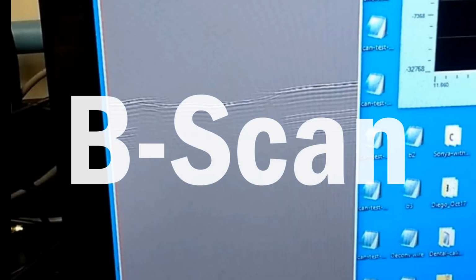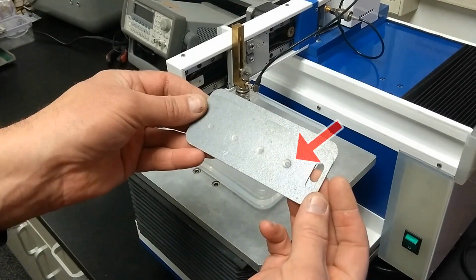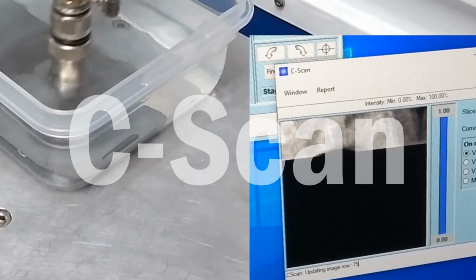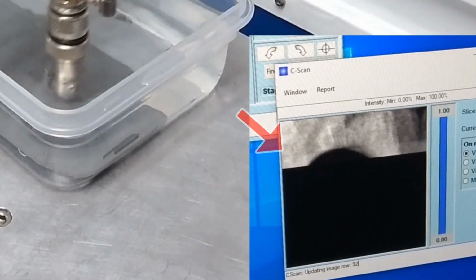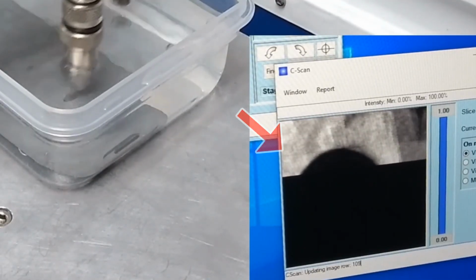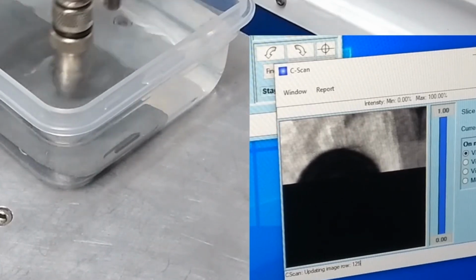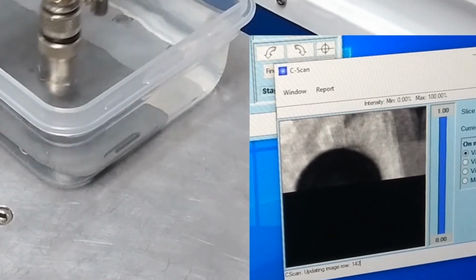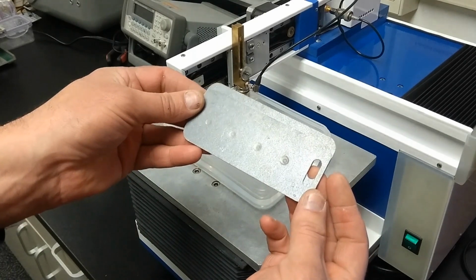On a B scan, we can expect to see horizontal lines, representing reflections. The fused nugget area should interrupt these lines. On a C scan, the software will compile an image of the sample. A dark black area will show the fused nugget, while lighter gray regions represent unfused areas.